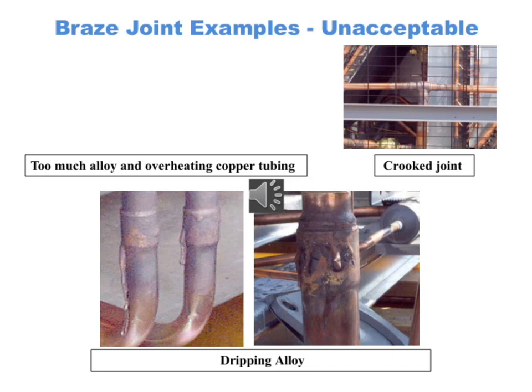Now, let's take a look at some examples of unacceptable braze joints. First, we have dripping alloy, which indicates that the alloy has not been applied properly and is running or dripping down the joint. This can compromise the integrity of the connection and lead to leaks or failures later on. Next, we see a crooked joint, where the alignment is off. Proper alignment is crucial for a strong, reliable bond, so a crooked joint can cause stress concentrations and reduce the overall strength.